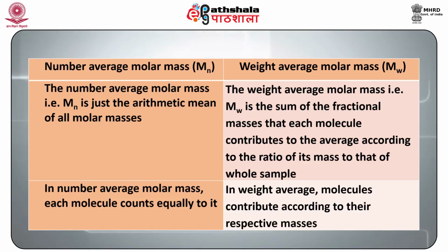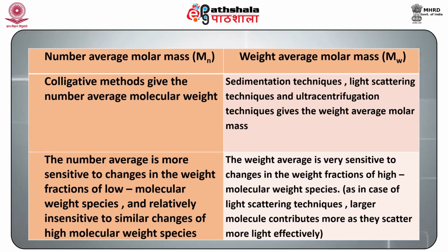In number average molar mass, each molecule counts equally to it. In weight average, molecules contribute according to their respective masses. Colligative methods give the number average molecular weight, whereas the sedimentation techniques, light scattering techniques and ultracentrifugation techniques give the weight average molar mass.